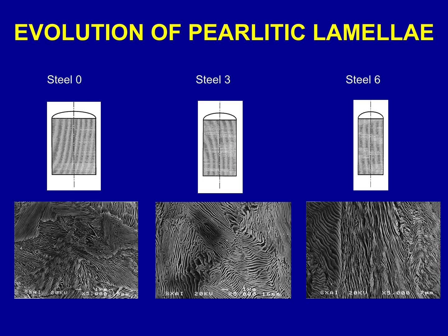With regard to the evolution of pearlitic lamella, ferrite cementite lamella for steel 0, 3, and 6, with 0, 3, and 6 drawing steps, in steel 0 we have in the longitudinal axial metallographic section an isotropic, randomly oriented microstructure. Steel 3 exhibits a more or less oriented microstructure, and steel 6 is like a microcomposite or nanocomposite with a marked orientation of ferrite cementite lamella in the y-axis or cold drawing direction. It's like a micro or nano-laminate of ferrite and cementite.